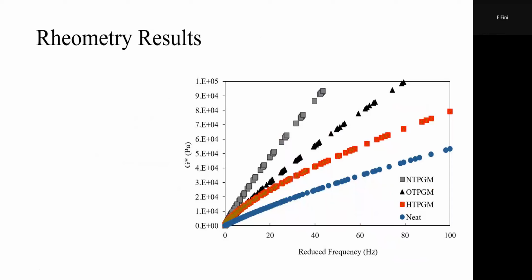Another method to show these materials are different is rheology or modulus. For those of you maybe not familiar with complex modulus, G star is a measure of resistance to shear. You basically shear the samples using a parallel plate spindle at a certain frequency, and you measure how much resistance it gives to that movement. Here you can see the neat asphalt is the blue. Neat asphalt, no plastic at all, was right here. As soon as we added each one of these plastics, it jumps up as expected. Think of adding granules or powder into the bitumen, which is liquid. So it becomes stiffer, with a higher modulus, more resistance to shear.